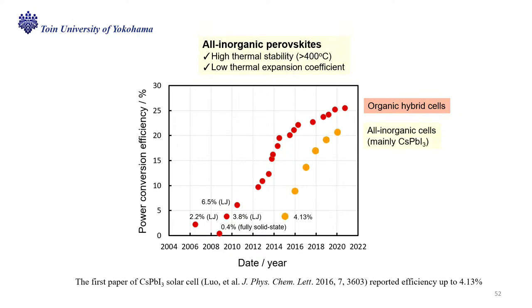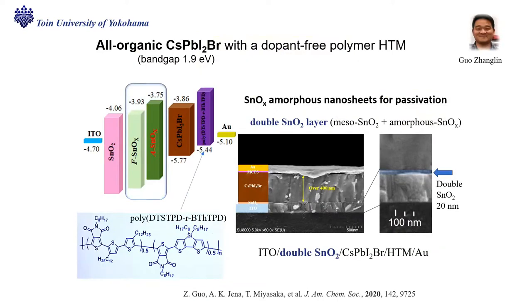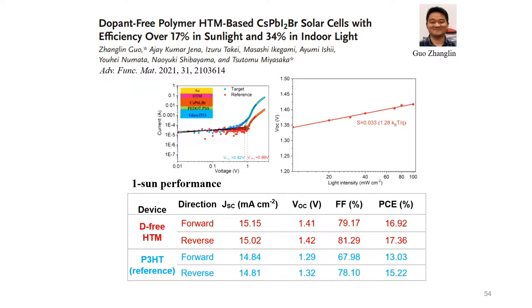But now we are tackling all inorganic cell, free of organic, because of very high thermal stability. So this is the materials, the cesium, lead, mixed halide. But this one was actually first synthesized in the late 19th century. Now we are doing this one as a light absorber. This is a conductive polymer supplied by Mitsubishi Chemical Company. And the result is this. Under sunlight, efficiency was not very high, 17%, but the photovoltage increased to 1.4.